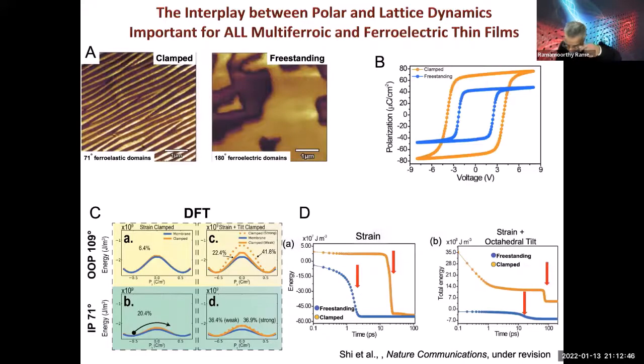Now, there's one thing I mentioned that the community has not paid attention to, which has to do with mechanics. If you look at the ferroelectrics field, the people who do piezoelectrics live in a different environment compared to the ferroelectrics field. So we'll take you through this piece of data. What you see here are domain structures. These are PFM images of a BFO layer, which is stuck to a substrate, and we call it clamped. I'm going to get to clamping in a second. And you can see this very nice ferroelastic domain structure.